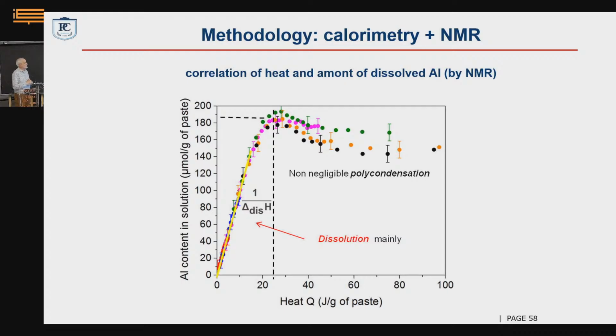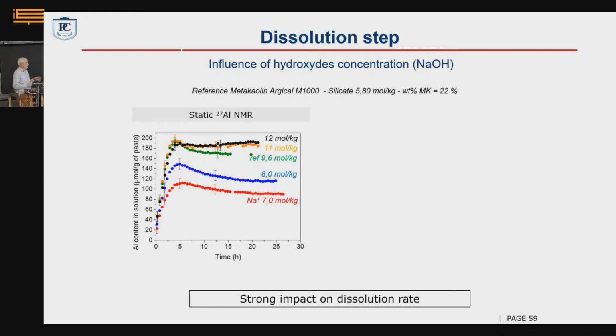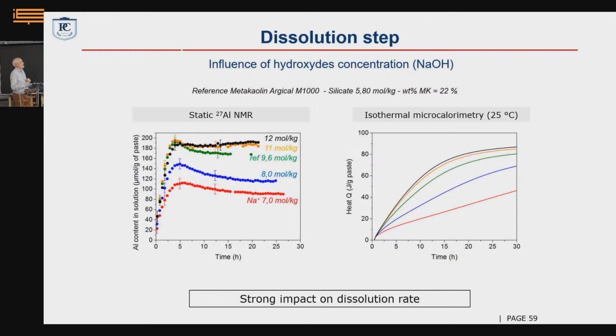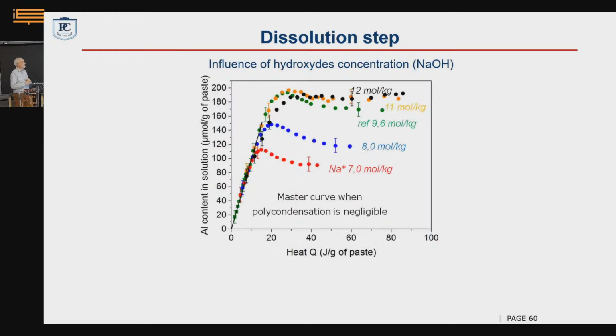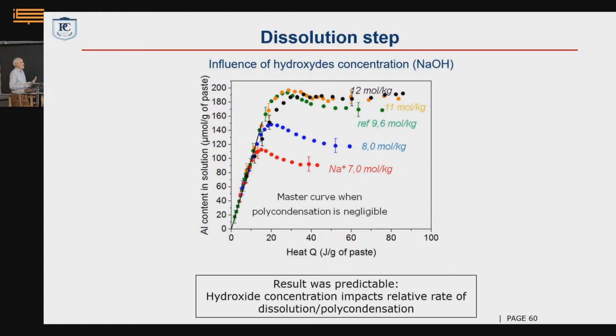And so my point here is to say that the inverse of this curve here is the enthalpy of dissolution, expressed by moles of aluminum. Okay, so if I do the same thing, varying the alkalinity, the amount of sodium hydroxide, different curves, different isothermal calorimetry, and same thing, master curve at the beginning. So whatever the concentration of sodium, the chemistry is the same. What changes here is how far the reaction goes. And this is normal because the more hydroxide I have, the more I can dissolve my metakaolinite. Okay? So this is not a big surprise. This is more a check that what we are doing is meaningful.